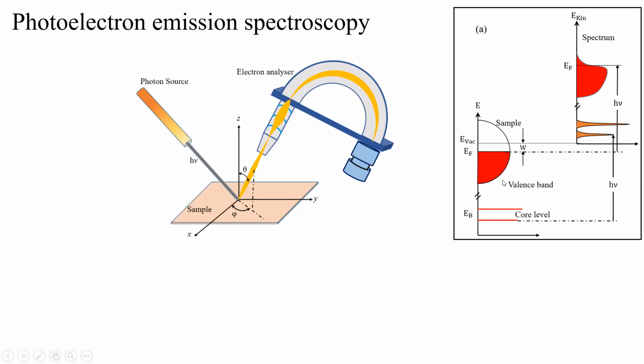Below this, the states are filled. Now, if you excite it using a photon energy hν, these states will go up here, and then you will get the spectrum. The broadening of these features is basically due to the lifetime of the hole that you have created, and also the resolution of the spectrometer. The broad feature that you see here is mainly due to the Fermi-Dirac distribution function at a finite temperature, and of course the spectrometer resolution also plays a role for this type of feature.